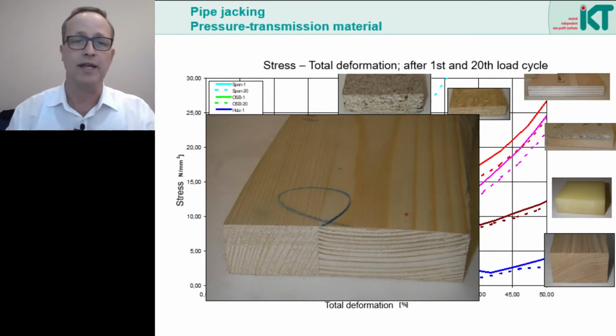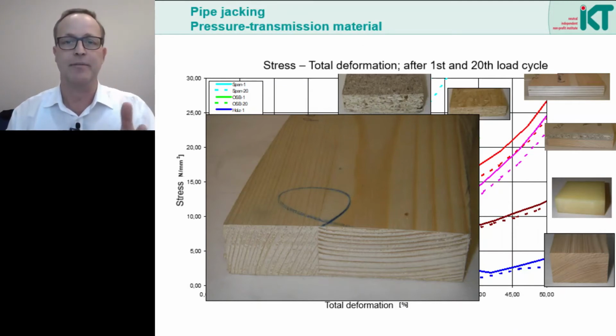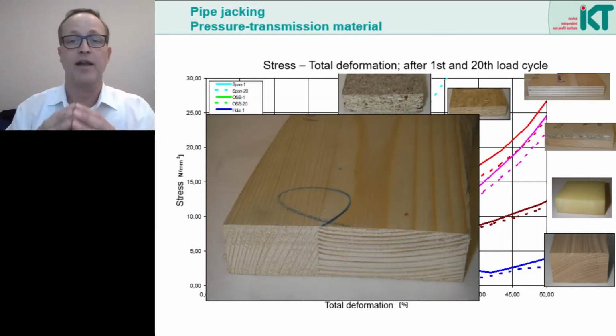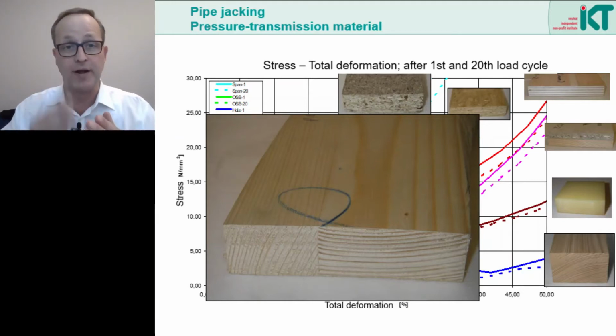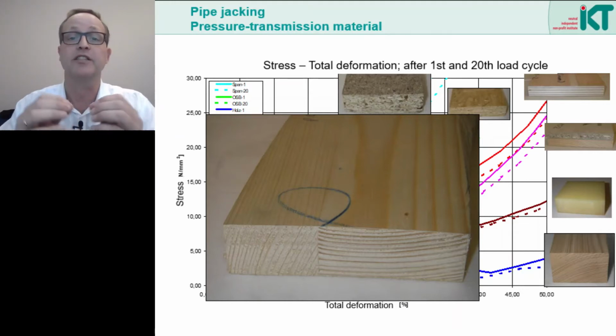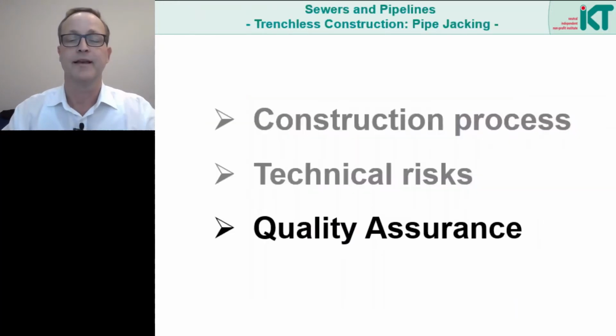Here we see a ring that was obviously assembled from 2 different solid woods with different fiber orientation. And this leads to uneven load-bearing behavior, because the strength in the fiber direction is much higher than transverse to it. And this brings us now to our research project, where we took a closer look at the quality influences and at the options for quality assurance.